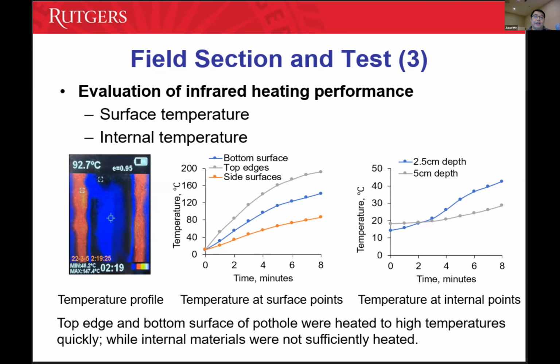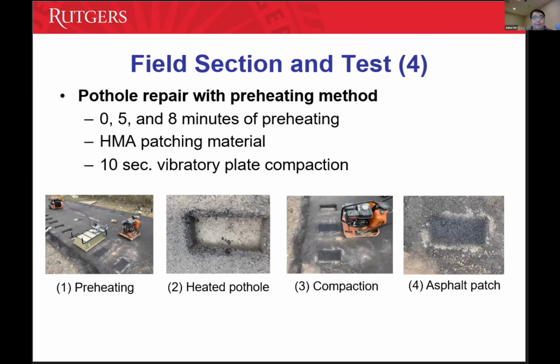That means infrared heating actually has much higher efficiency at the surface. In this case, we only have 2.5 centimeter and 5 centimeter depth. So in this case, you can see also the difference, the shallow one getting much higher temperature. So with that, we also conduct the repair.